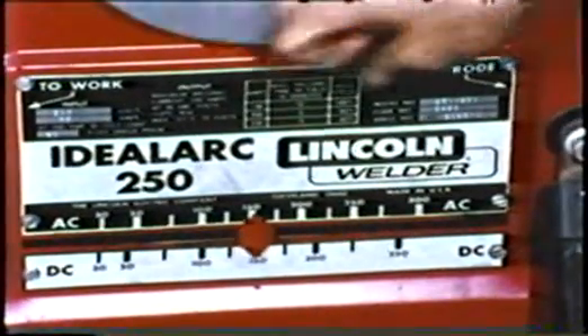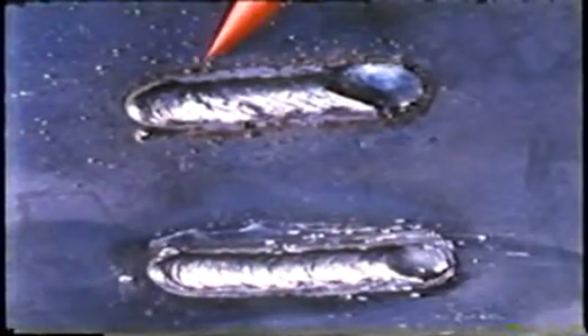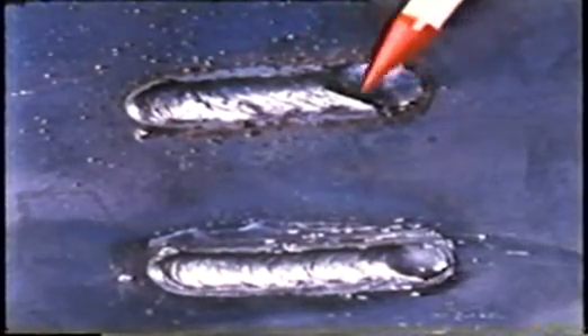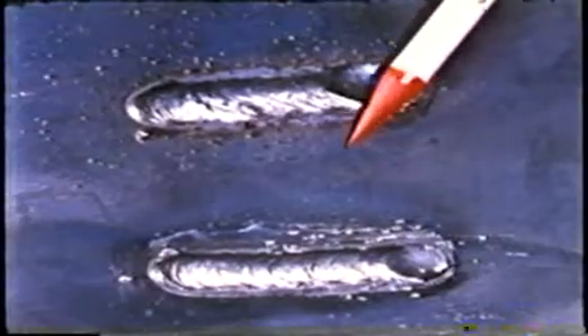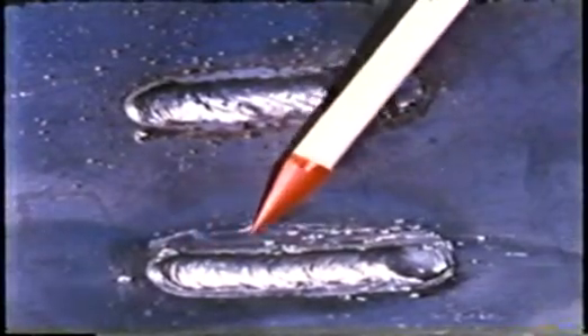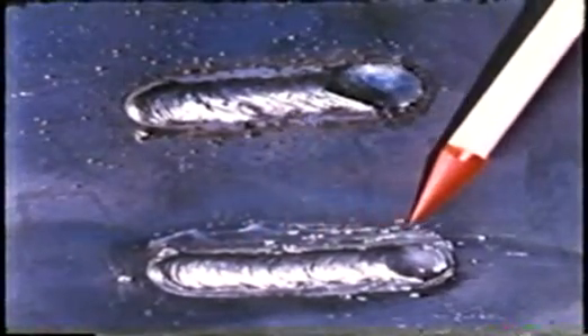If the current is set too high, the electrode melts too fast and the molten pool is large and irregular. Undercutting and excessive spatter will also be noted when the current setting is too high. This is a correctly made weld bead at lower amperage.